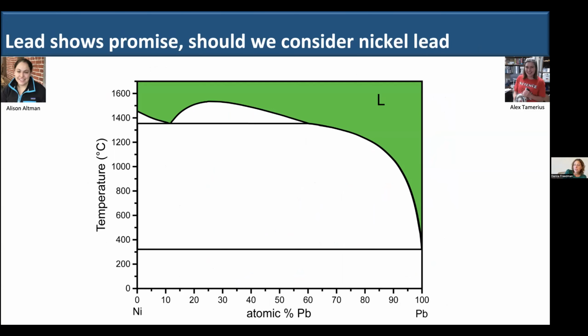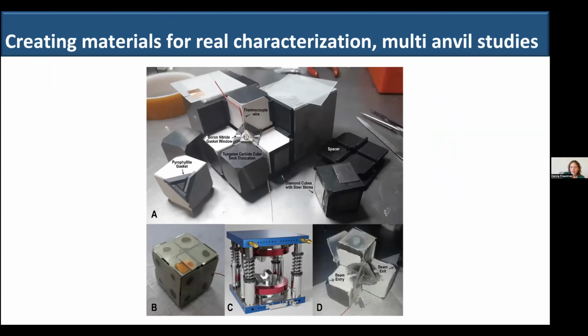So we can continue our exploration with lead and move from copper to nickel. And again, there are no binaries in the system. And if we want to measure physical properties, we should probably look not just at diamond anvil cells, but at the multi-anvil press. A schematic of the multi-anvil press is shown here. Here we can form materials that we can actually hold on to. And I should have been more specific with that earlier.